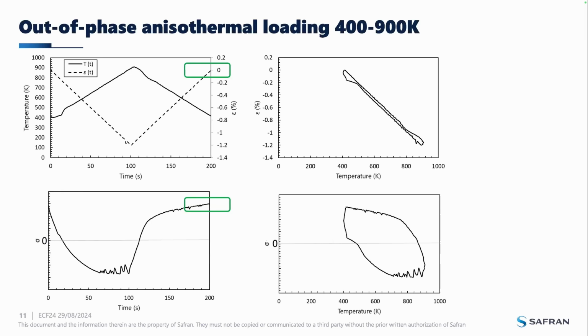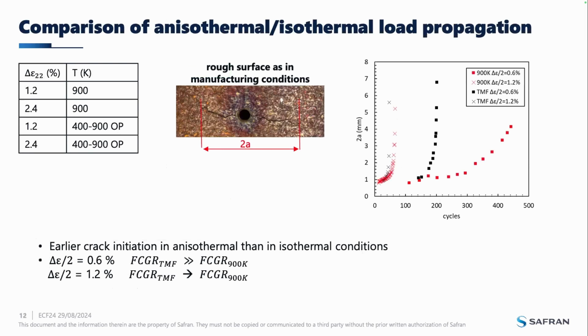And so at high temperature, the stress is negative, and then at low temperature, the stress becomes widely positive. So I measured crack length the same way as the other tests. And here the surface is rough because of manufacturing conditions. And so I was able to compare anisothermal and isothermal loading influence for crack propagation.